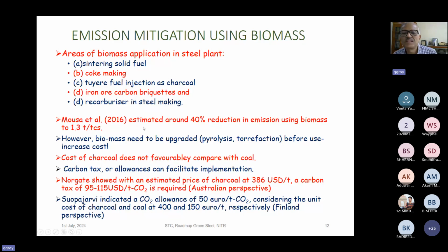Mousa et al. estimated that a 40% reduction in emission by biomass is possible, and that we can reduce the carbon emission from 2 to 1.3 ton per ton of crude steel. But one thing is that biomass needs to be upgraded, because biomass contains a lot of volatiles and the carbon is not concentrated. So you have to concentrate the carbon, and for that you require some pre-treatment, called pyrolysis or torrefaction, such that you can concentrate the carbon and then improve the quality of the biomass for subsequent use.